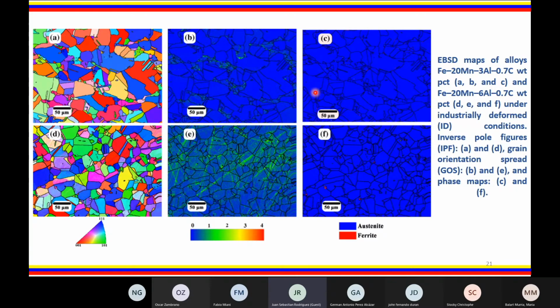The dynamic recrystallization process produces grains with random orientation. On the other hand, it is observed that the degree of misorientation of these samples is very low, which corroborates that the condition of this microstructure is that of newly formed grains as a result of the recrystallization process. And finally, this process does not generate phase transformation at the working temperature.